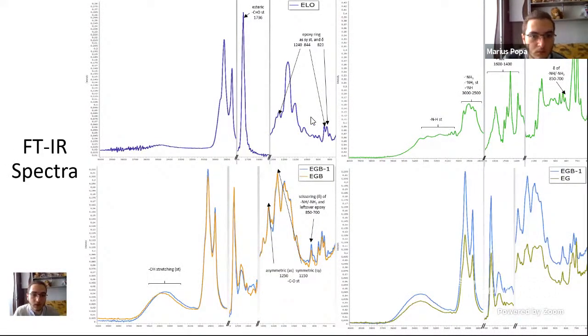Firstly, we investigated the consumption of the reagents and the finalization of the reaction by FTIR spectra. We can find the expected characteristic bands for ester carbonyl stretching, epoxy ring symmetric and asymmetric stretching, and also scissoring of the epoxy ring here, and here. On the hardener side, being a mixture of different compounds doesn't help with the interpretation, but we can find the general ranges for different compounds here.